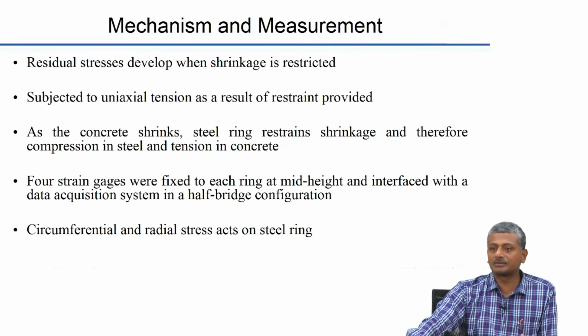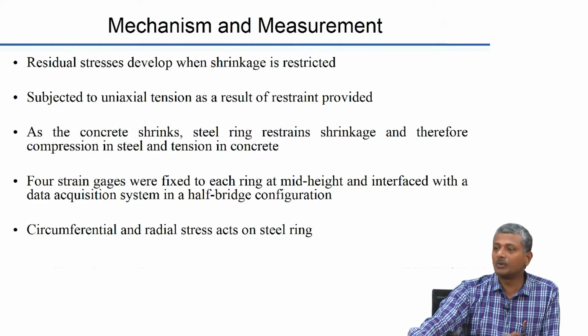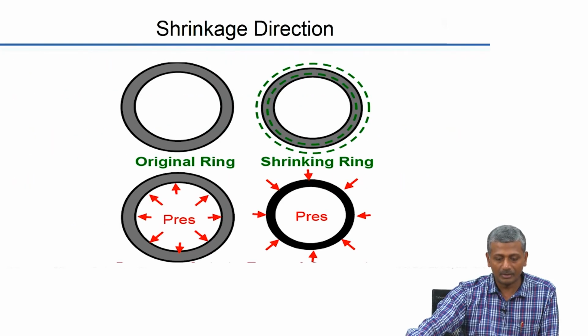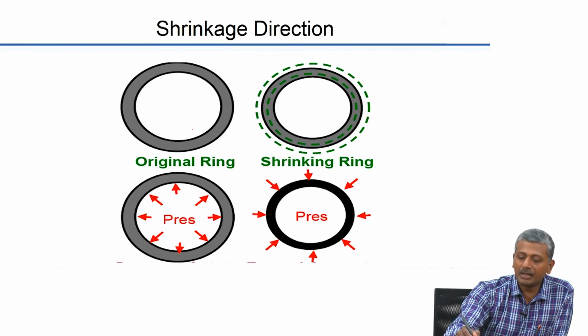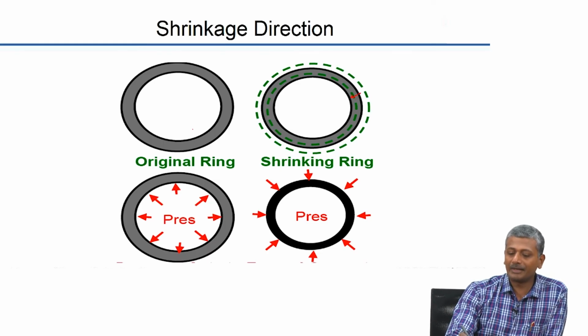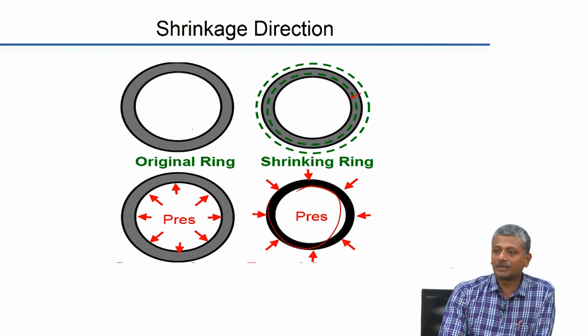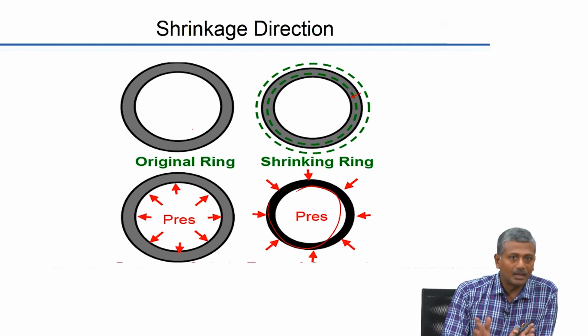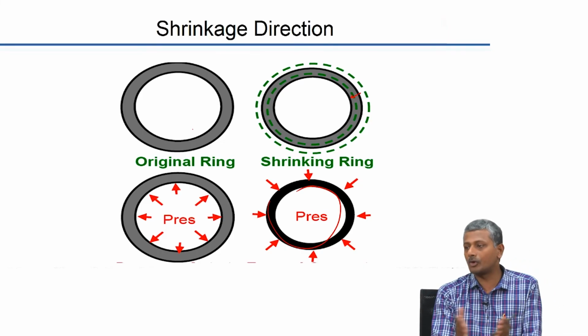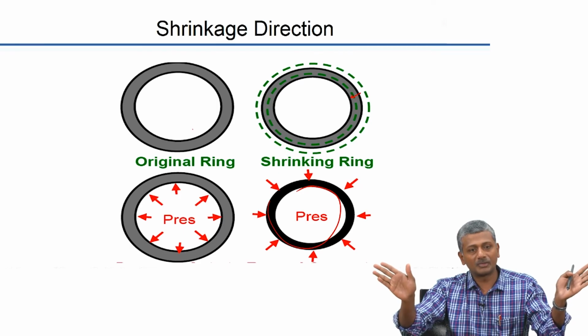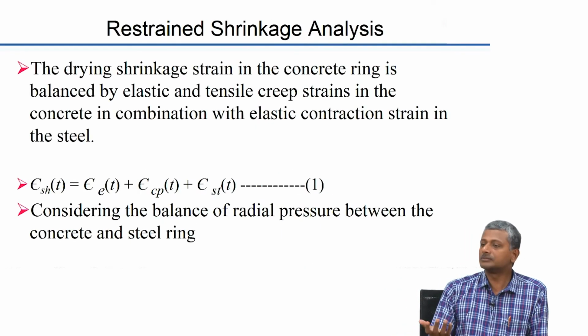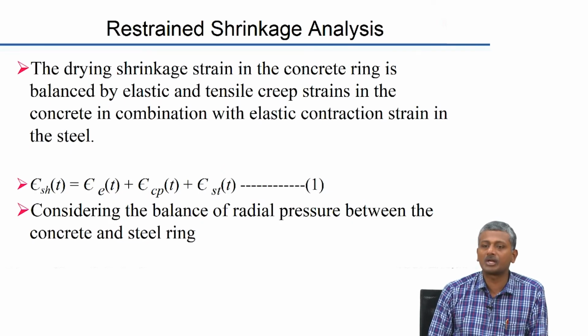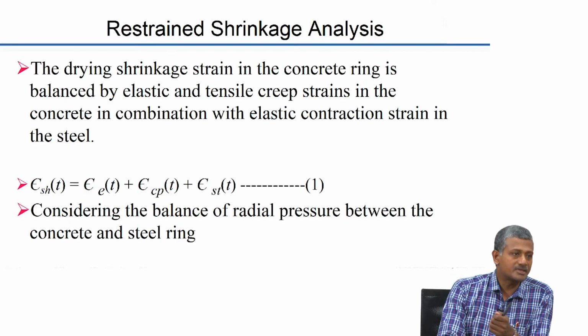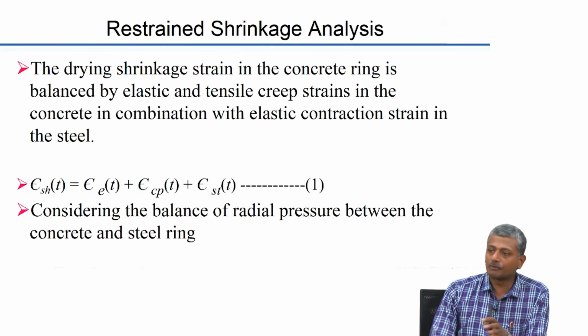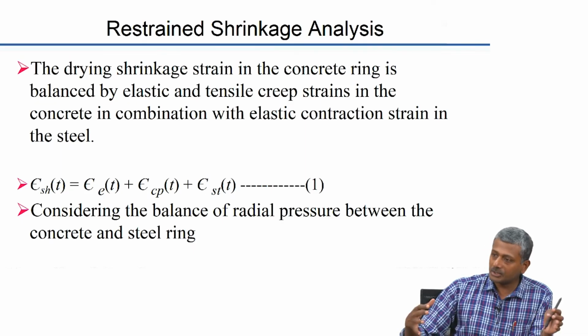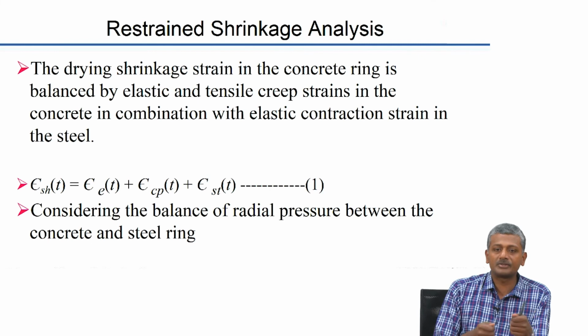So, again what you do is measure the residual stresses that develop in the concrete when the shrinkage is restrained by the steel ring that is inside. Okay. So, again this is your original ring, and when you have a shrinking ring, essentially the concrete tries to shrink inwards, and that creates pressure on the steel ring, and that pressure is almost equal to the pressure that is on the concrete ring. Restraint pressure, because every action has an equal and opposite reaction. So, pressure on the steel ring is equal to the pressure which is restraining the concrete from shrinking, and the steel ring pressure can generate strains in the steel ring, which can be measured in terms of the hoop strains, and those hoop strains can then be converted to the actual stress in the steel. Of course, we consider that the overall shrinkage which happens in the system is equal to the strain that is getting produced in the steel. Okay.